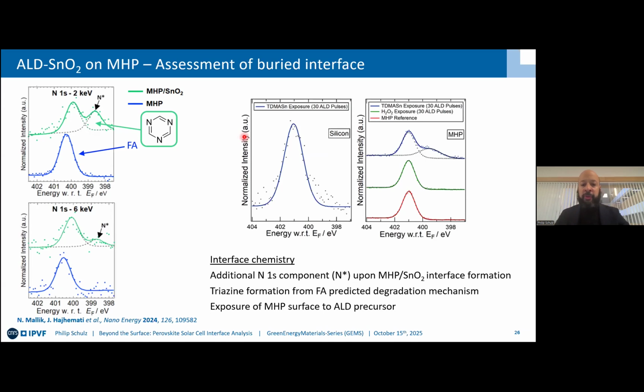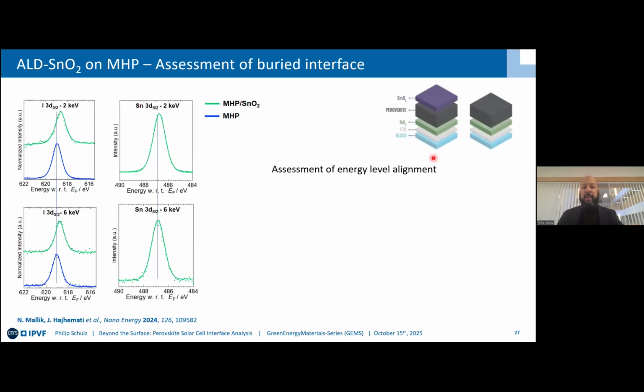And we also, of course, tested the exposure of the surface to the ALD precursor, and were able to see the formation of what we suppose is s-triazine. So a lot of interface chemistry going on.